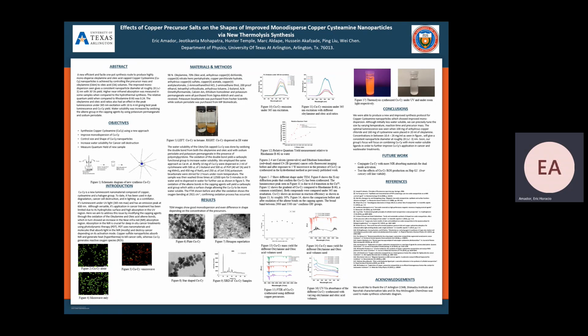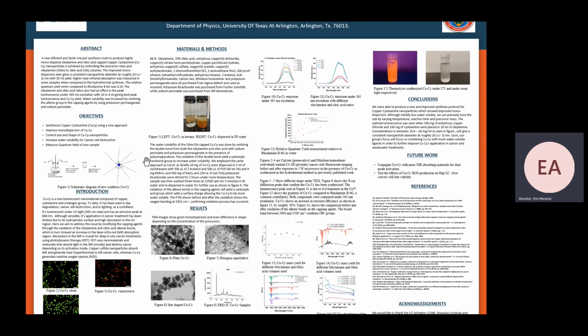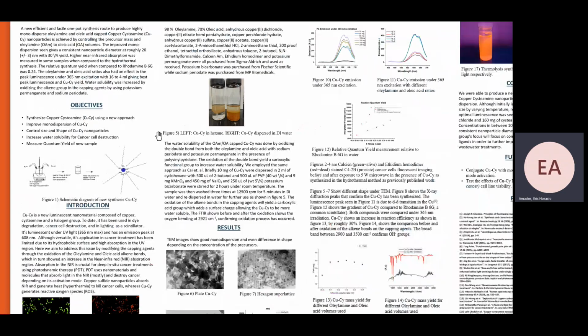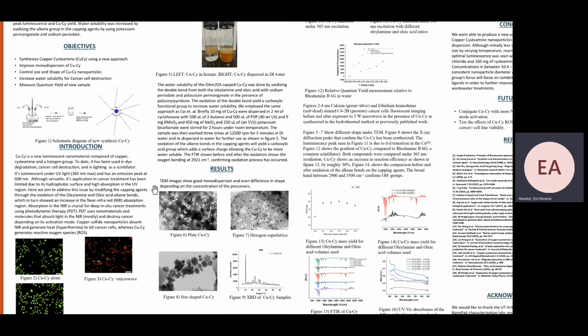We improve this monodispersion in order to improve the cancer-killing effect of copper cysteamine. However, this new approach uses oleylamine and oleic acid, which are going to make the nanoparticle hydrophobic instead of hydrophilic. So there is a trade-off.